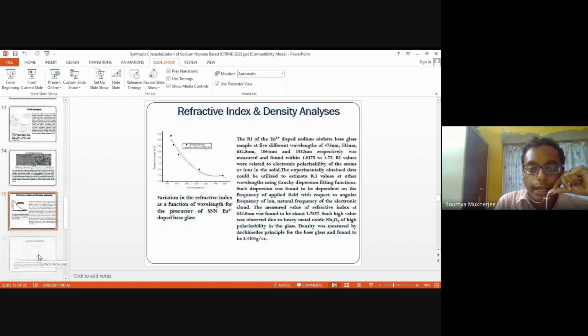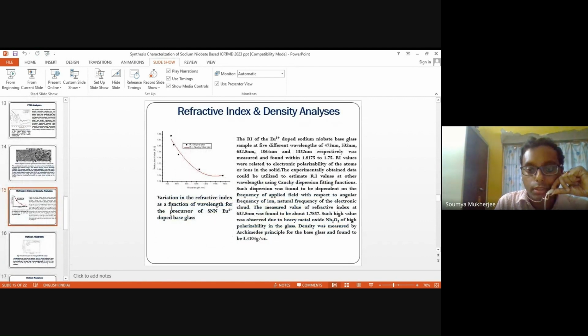After that, we carried out the refractive index calculations using a prism coupler, and the refractive index of this system was fitted with Cauchy's equations. We found the refractive index at 5 different wavelengths: 473 nanometers, 532 nanometers, 632.8, 1064 and 1552. It is as per standard, and we found that it varies between 1.81 and 1.75. If we observe the value at 632 nanometers, it is close to 1.78.